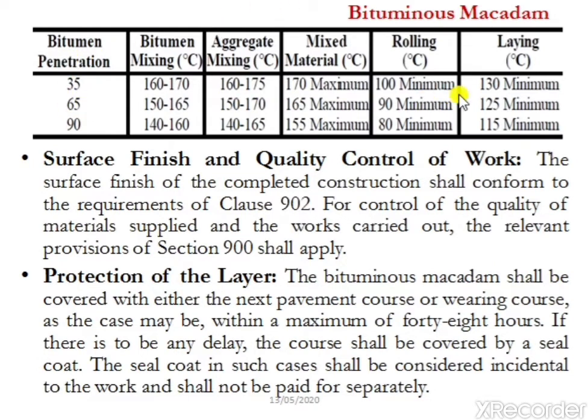So in this table you can see the different specifications for the bitumen. For a bitumen with a penetration of 35, the bitumen should be mixed at a temperature between 160 to 170 degrees, and the aggregate mixing is between 160 to 175 degrees, and the mixed material should be used at a temperature of 170 degrees, and that is the maximum temperature for the mixed material. So mixed material means the mixing of bitumen and aggregate.